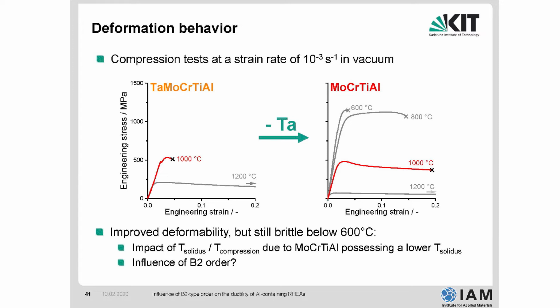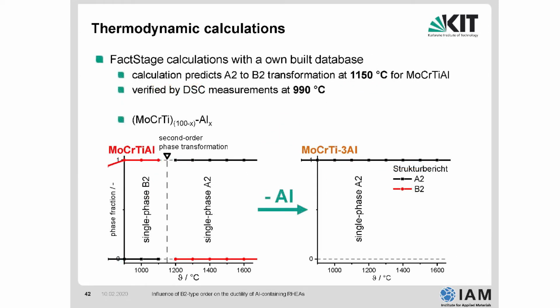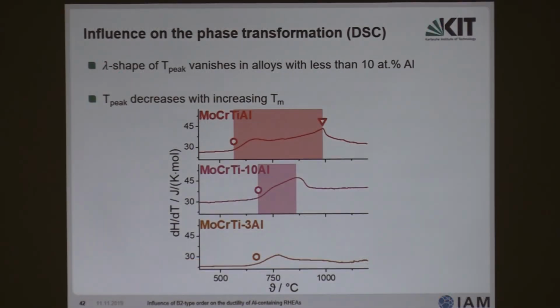So the question you could now pose is, is there an influence of B2 order? And we did some calculations with a thermodynamic database to verify whether there is an A2 to B2 transformation at 1150 degrees Celsius. This is what it shows here. There should be a second order phase transformation at 1150 degrees Celsius. So we expect a B2 ordered structure to form. Whereas if we reduce the aluminum content, it should be single phase all the way up to the melting point and all the way down to room temperature. So the final 2 slides I'm showing are on this alloy with the reduced aluminum content.